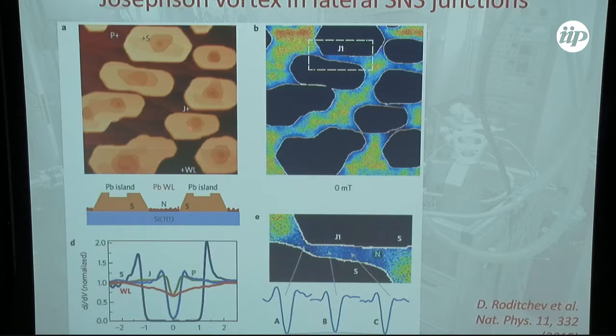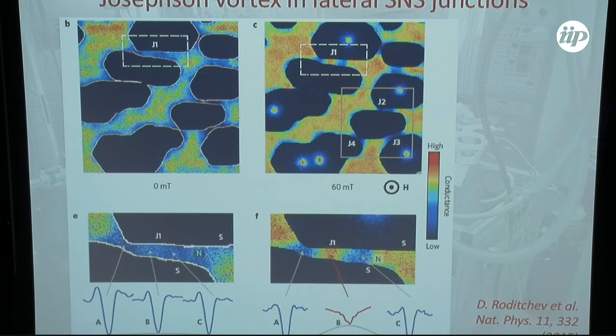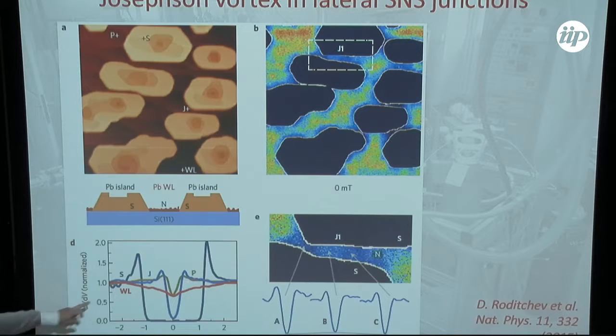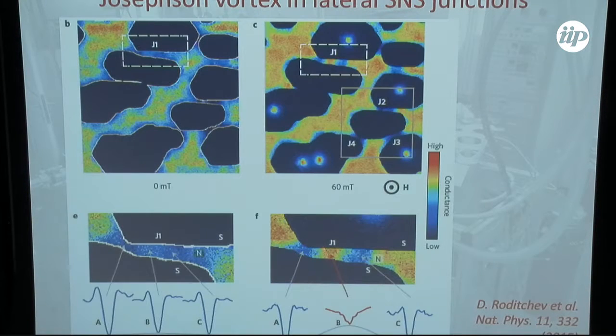How do we do it? For instance, between two islands, you clearly see this Andreev gap. This gap is much smaller than the superconducting gap in both electrodes, because it is not a superconducting gap, it's just a proximity gap. Now, if you apply a magnetic field, you can destroy superconductivity in one location, and this is nothing more than the core of the Josephson vortex.